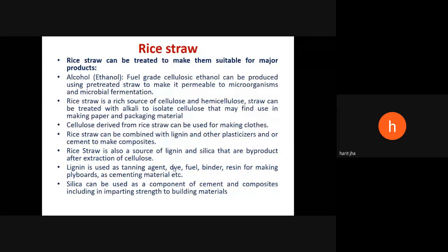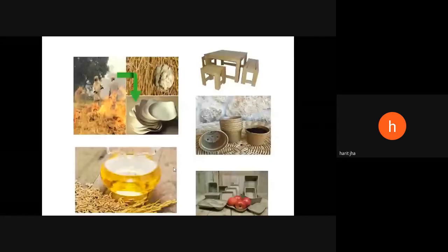Rice straw is also a source of lignin and silica that are byproducts after extraction of cellulose. This lignin can then be used as a tanning agent, dye, fuel, binder, resin, etc. for making plywood, as cementing material, and many other uses are there for the lignin. The silica which remains after extraction of lignin and cellulose can be used as a component of cement and composites, and that imparts strength to the building material. These are some of the examples.